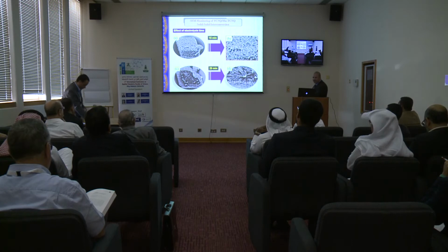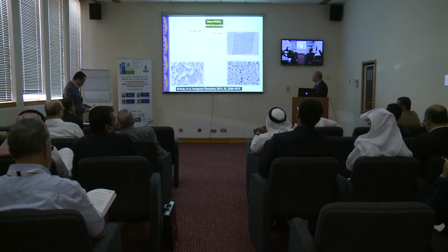So how do we monitor this? Actually, we start with an electrode like this. We put it into 0.1 molar of manganese. We apply a potential. We get this kind of fibrous material of manganese TCNQ network. When you cycle this for about 5 cycles, you can see that some of them start to grow big at the expense of the fibrous material. When you give it more time, you can get the same material highly resolved. So this is, again, a different morphology of these materials.